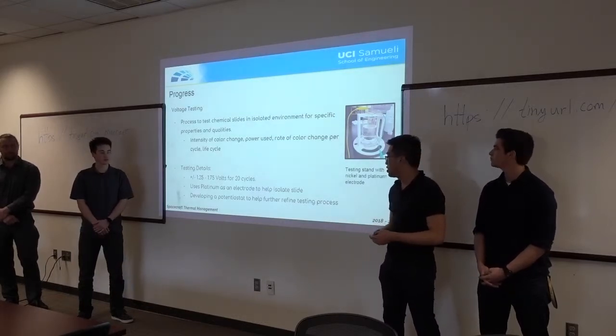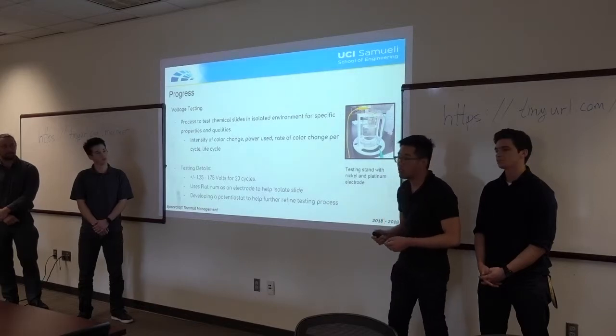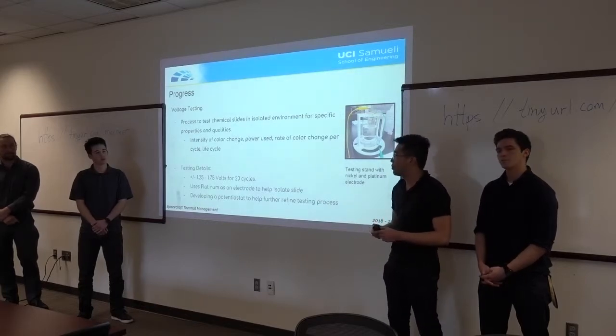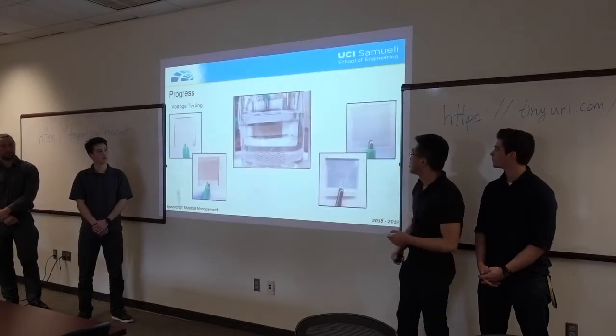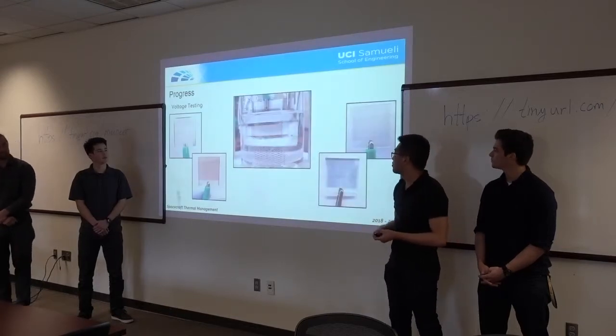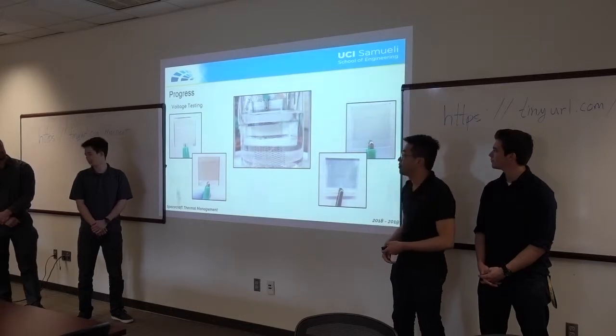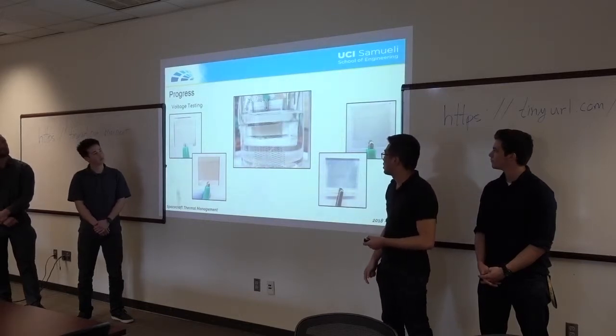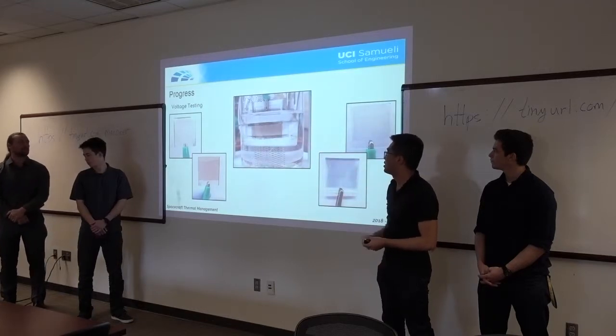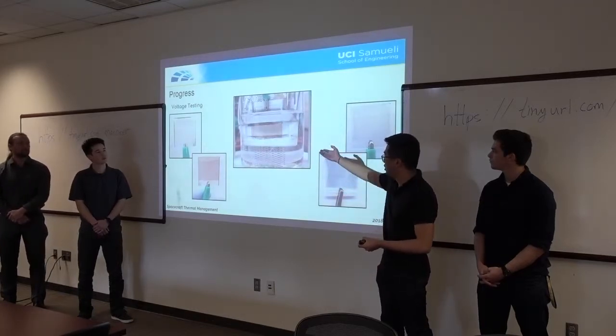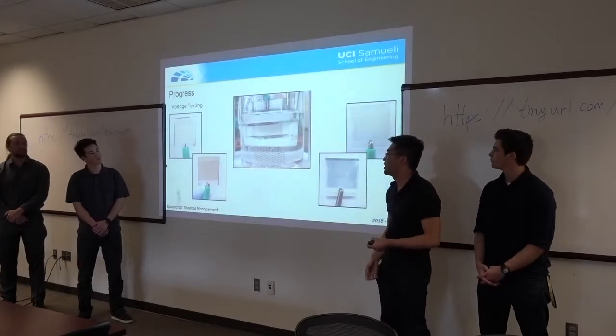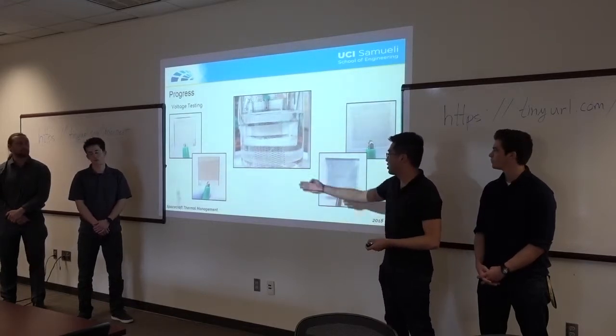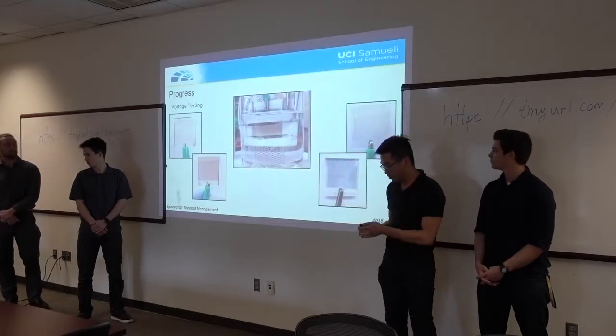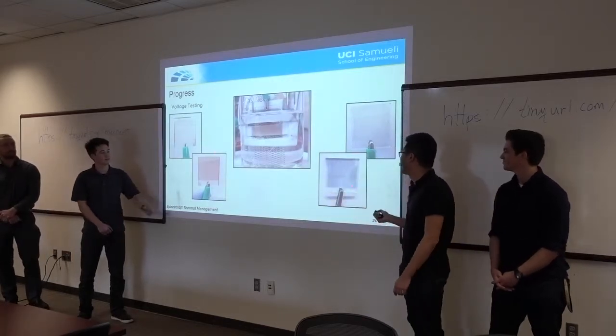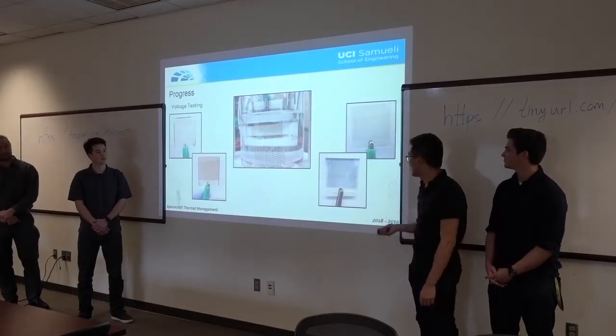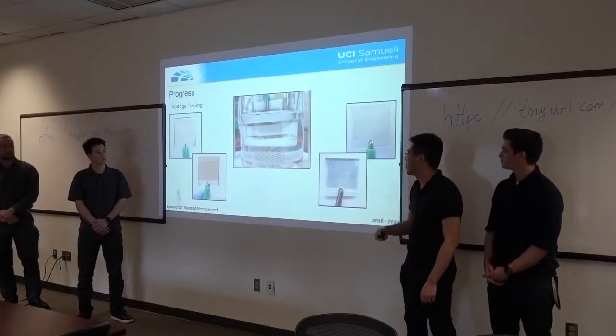And currently we're developing a potentiostat to help further refine the testing processes, since our voltage system needs a little bit more refinement. So we have a little GIF here. It's sped up like 0.2 times faster. So if we flip the voltage one way, that's the color it changes to. If we flip it the other way, it turns to a bright, nice, clear color. So that's what our tungsten slides look like on the right over here. And this is what our nickel slides look like. If it were a little darker, you would see this is blue and this is a little bit brownish.